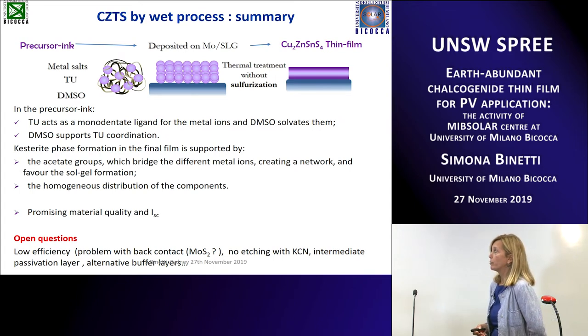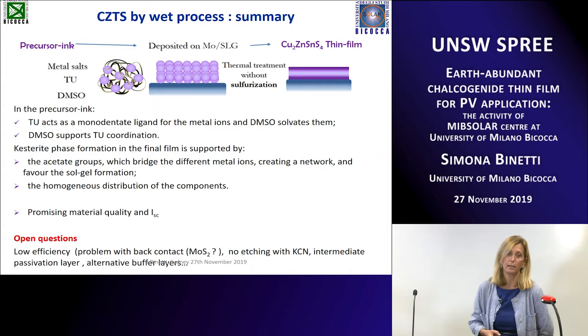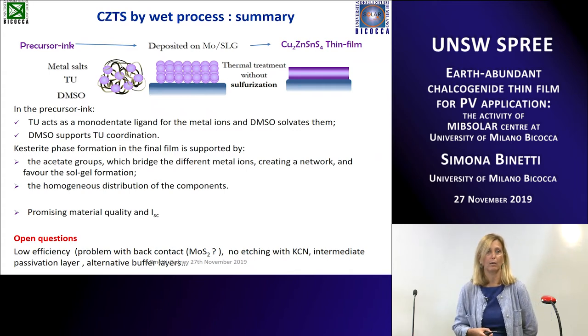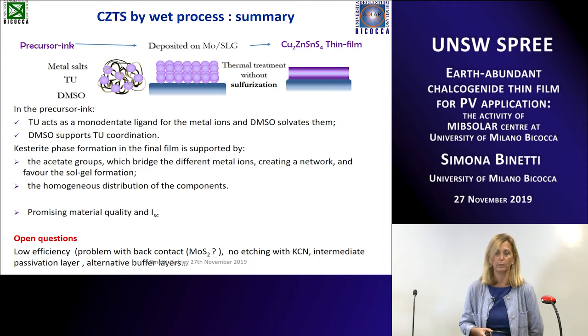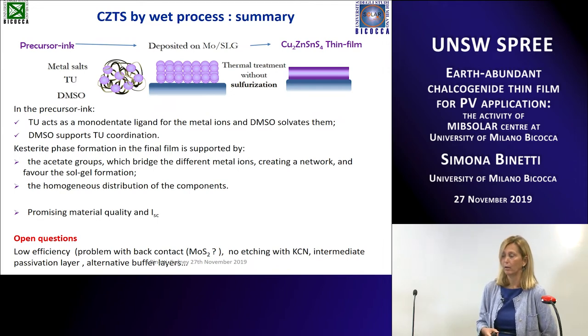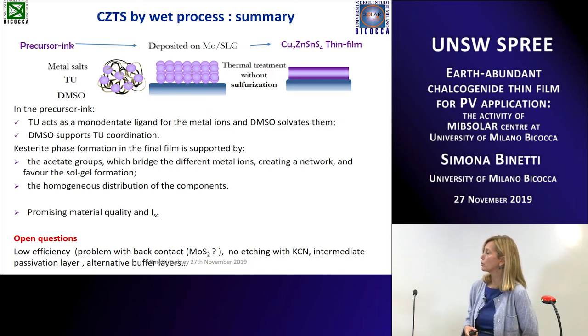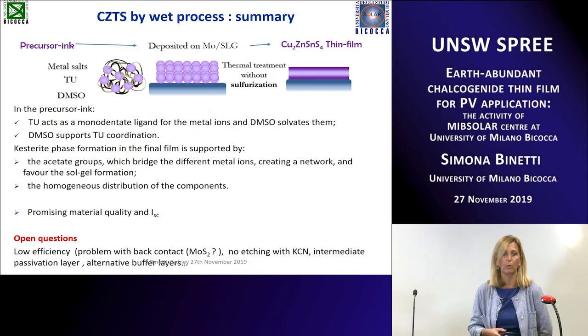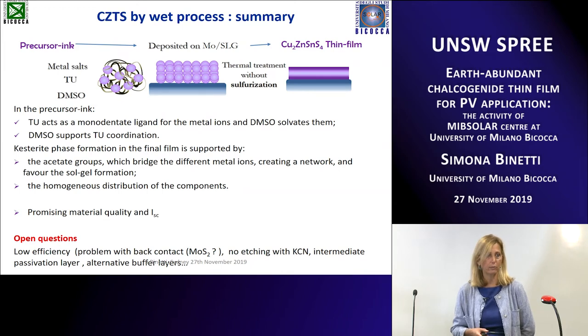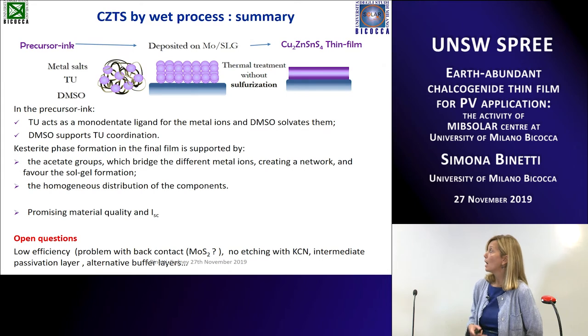We have a problem with the back contact. For instance, we have seen that we have a quite thick molybdenum sulfide at the back, formed during the annealing thanks to the thiourea. So we have to check again the thiourea concentration and also the annealing, because at the moment we are performing standard annealing steps, not RTA, rapid thermal annealing. We don't use any etching with KCN, so we may have some problems at the surface.